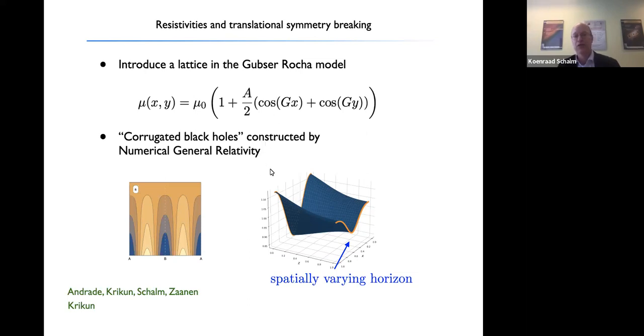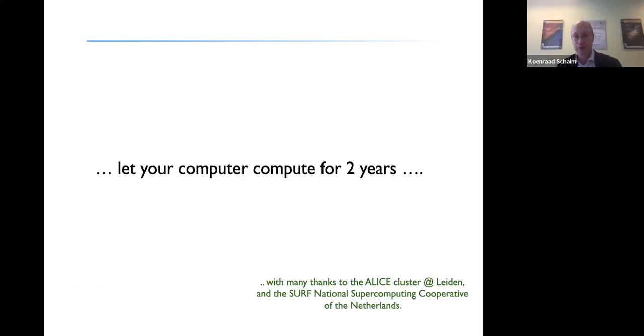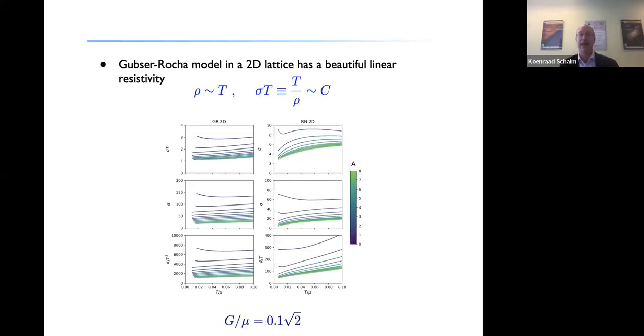So these are black hole solutions that, because they're still at finite temperature, have a spatially varying horizon, and you have to really solve a large set of, in this particular case, three-dimensional partial differential equations to construct these solutions. So you do that, you let your computer compute for 2 years, and then what you get out is you can read off through the AdS/CFT the response functions.